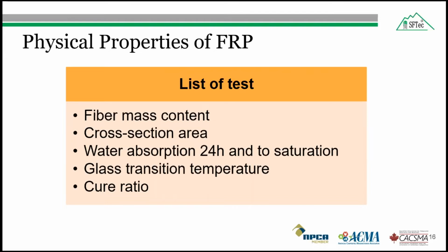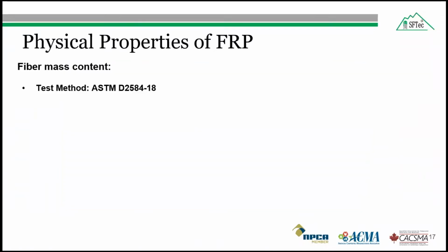So the following properties should be tested. The test method for the following property will be discussed one by one, starting with the fiber mass content. So the fiber mass content, the specimens were generally cut to 1 inch for fiber mass content. And tested in accordance to the ASTM D2584, which was released in 2018.